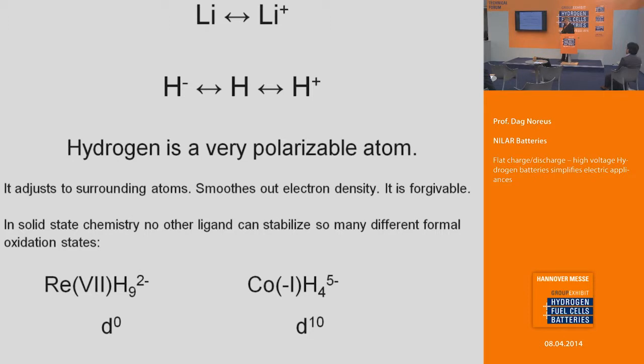And so the hydrogen is flexible. It adjusts to the surrounding atoms, smoothes out electron density. It's very forgiving as an atom. And if you look in solid state chemistry, there is no other ligand that can stabilize so many different formal oxidation states. You have rhenium, formal oxidation state 7, a d0 state, all the way to cobalt, d10. It's 8 oxidation steps. No other ligand can do that. So in a way, hydrogen is very unique. And I want to emphasize the uniqueness here when you do it in batteries. That simplifies a lot of things.